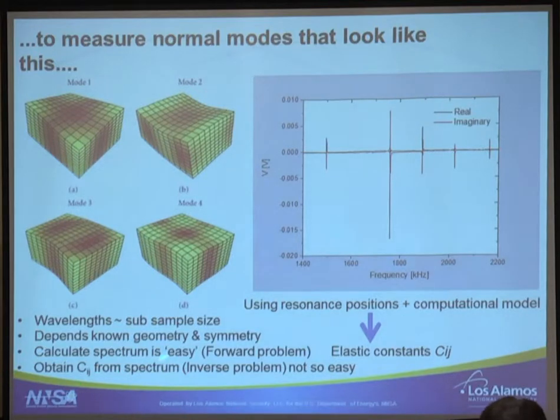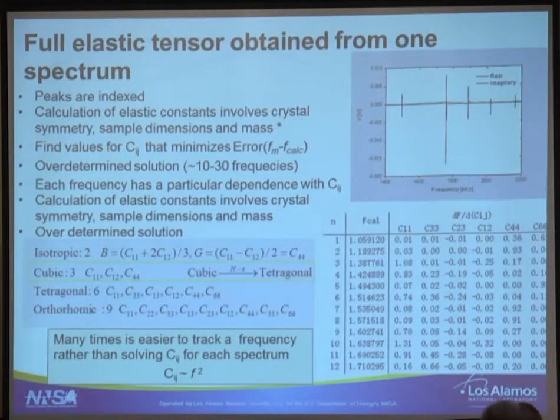Anyhow, once you have the elastic constants, it's fairly easy to calculate the position of the peaks, the forward problem. So you know your elastic constants, you can see, okay, I will have a resonance here, here, and here. Now, the inverse problem, having the resonances and then getting, let's say, 6 elastic constants, was something that was only solved in the late 80s. And at the time, it took considerable computational effort. Now you can do it on your PC in half a second, not half a minute. So now the problem of starting with the peak positions and getting the solution is much simpler.